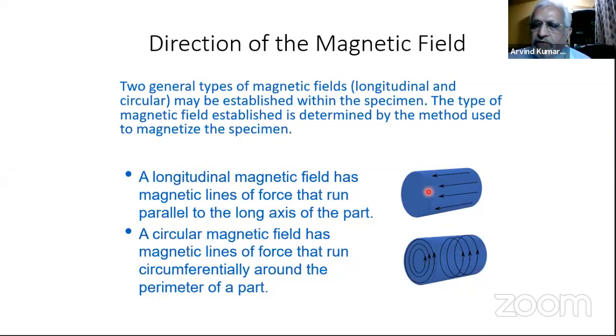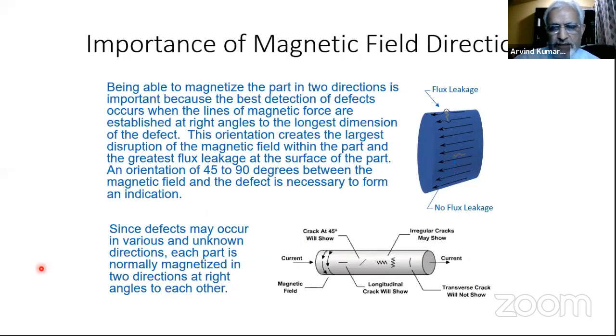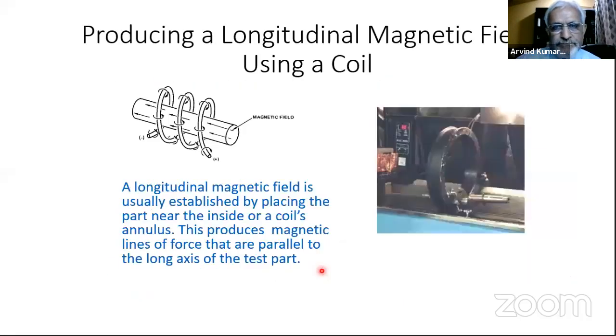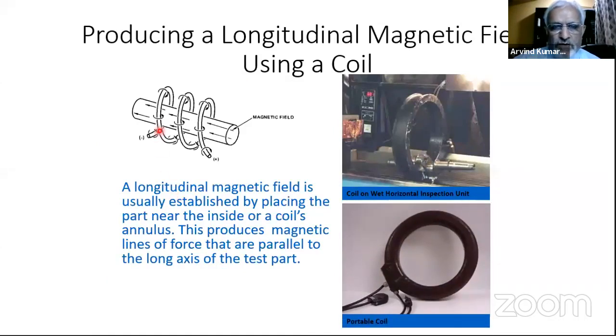And that is why, for each MPI, I will show in the next one where there is a yoke, you will have a better idea. Like here, for this field, you will see a longitudinal defect, and this type of defect, which is across the circumference, will not be picked up in this. Now this is again generating a longitudinal field because the encircling coil is there, and the field will be like this, and you can find defects which are transverse to this field.